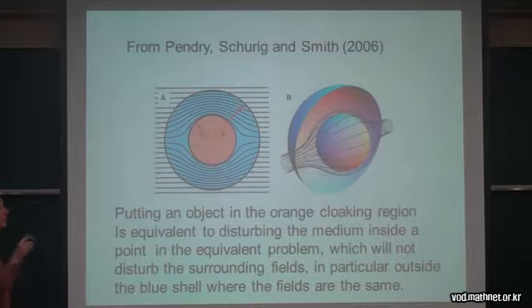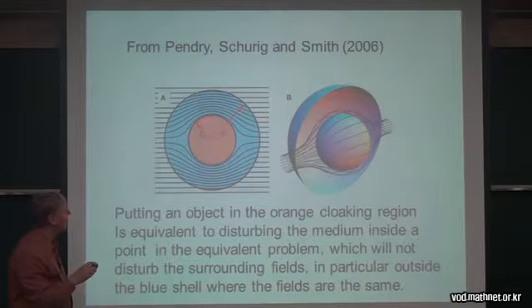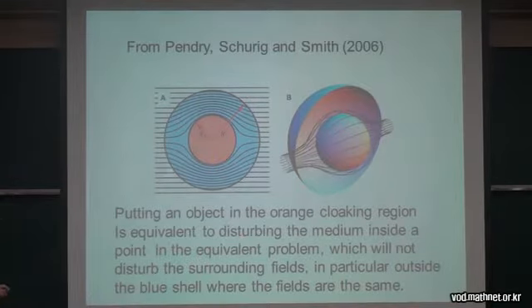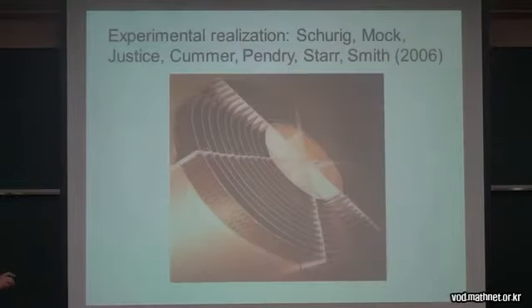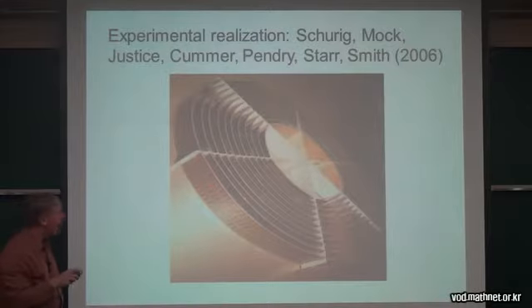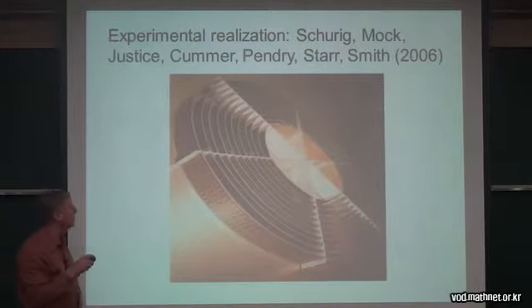Pendry, Schurig, and Smith did the same thing for electromagnetism, including, this is for showing light rays, but basically it's the same idea. And you can put an object inside this region and it will remain cloaked from the outside. And this was experimentally realized by Schurig, Mock, Justice, Cummer, Pendry, Starr, and Smith in 2006 with this geometry using metamaterials to get the artificial magnetic behavior that is needed for the anisotropic properties of the material surrounding the cloak.